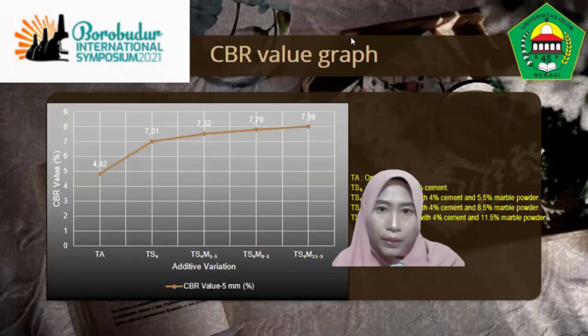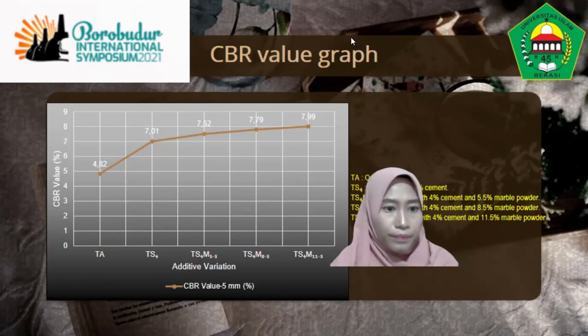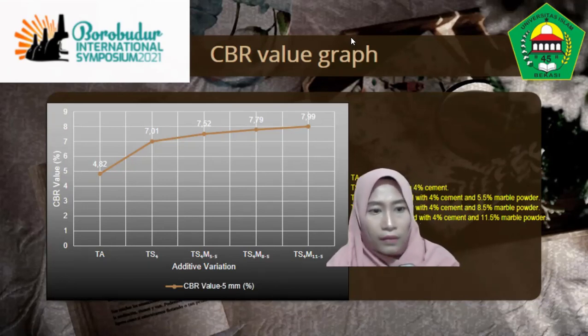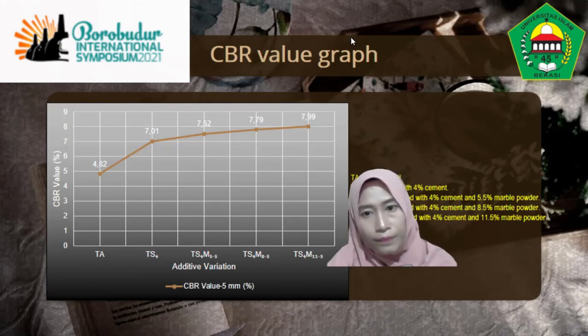This slide shows a CBR value graph. It was found that the highest CBR value was found in the variant TS4 M11.5. It's about 7.99%.